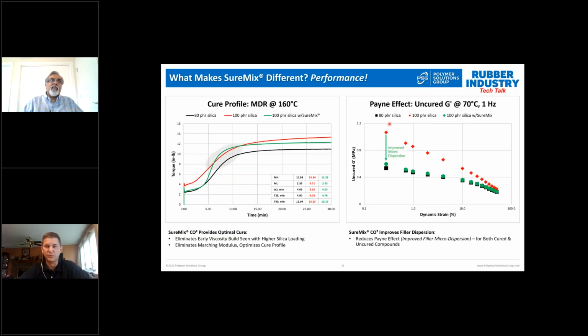Okay, so another challenge when you're going from 80 to 100 parts of silica or even higher, as Ricky mentioned, is that there's often an effect on the cure. Right, the more silica you have in the compound, the more absorption of accelerators you're going to get to the silica surface. So you see going from the black to the red curve, you see a couple things. You see the flocculation of the silica early on, which causes the earlier increase in the viscosity. And then you also see the marching modulus of the compound. So you see the red curve continues, instead of being a plateau, it continues to rise. So that can be caused by the accelerators being absorbed to the silica surface and then over the course of the cure being released from the silica surface.